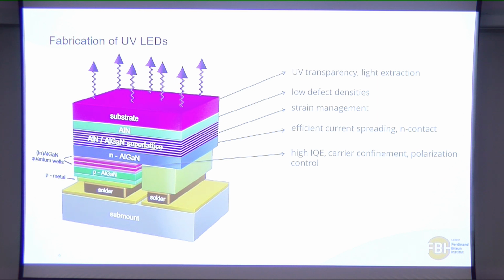So you need to control all of this in this active region. And then you have the n-AlGaN current spreading layer. So basically, you want good conductivity here. It's really difficult because now you have high aluminum gallium nitride, so it is difficult to make a conductive layer over here. And ideally you would like this layer to be transparent, because if it was transparent, then any light that is emitted in this direction, if you have a mirror over here, you can reflect it out of the system. So that way you can also collect the light which is emitted towards the P contact. So that's what you want to do. That's really difficult to do.